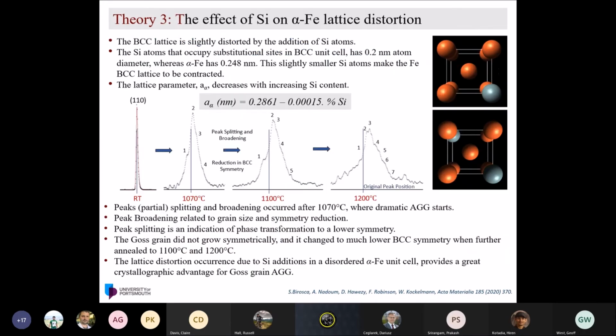So we try to understand this further. We look at the peak shifting, splitting and broadening. As I stated in the first few slides of my talk today, in BCC when you add silicon, because silicon has a smaller atom size, the lattice will be distorted and slightly contracted. The lattice parameter is proven to decrease with increasing silicon content. So if you look at the peaks, you will see the 110 peaks shifting, and then some peak broadening and partial peak splitting.